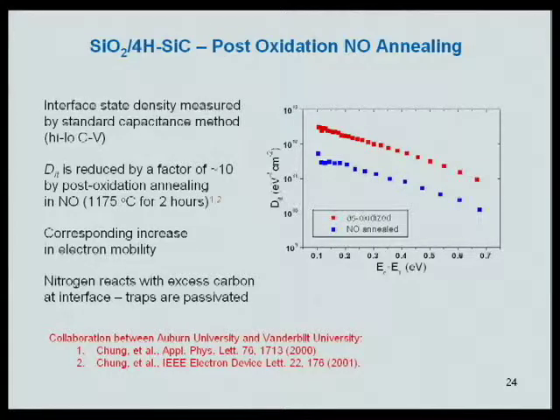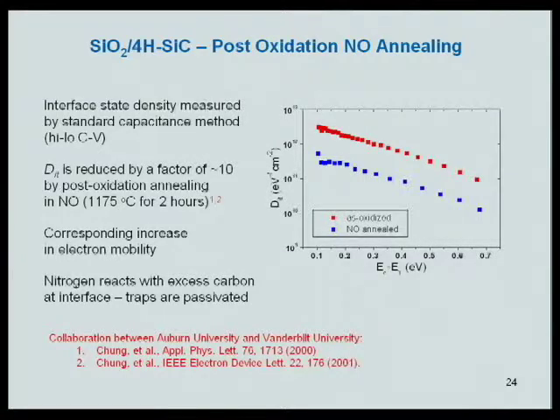Now, a few years ago, there's been a long-standing collaboration with two groups, one at Auburn University, Professor John Williams, and one at Vanderbilt University, Professor Len Feldman, and they discovered that if they exposed these samples to NO at high temperature, and here this shows data for high temperature annealing for 2 hours, the defect density was reduced by an order of magnitude. Again, we still see this exponential decay, but everywhere along it's reduced. This was actually a breakthrough. The fact that nitrogen could passivate 90% of these defects made it possible for Cree to introduce the first silicon carbide MOSFETs this year.